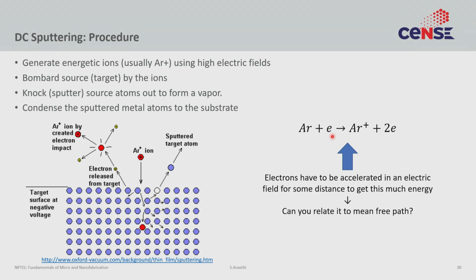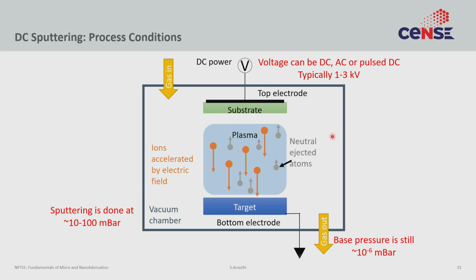So if the gas is very sparse, then your mean free path is long, so they will have a very long time to accelerate under electric field, generating a lot of energy. However, if the mean free path is small, they will not have a lot of energy. Just keeping that in mind, let's go next, right?